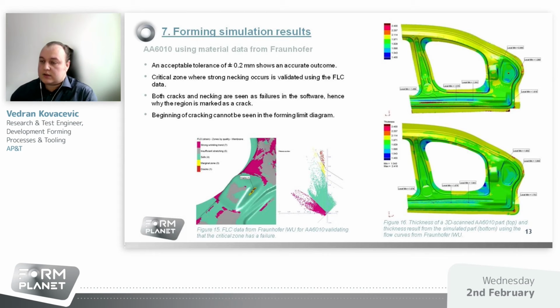Looking at the 6010 result, the simulation also shows accurate thickness behavior. The deviation in the critical zones is within plus minus 0.2 millimeter, and the zone where the strong necking occurs is validated with the FLC data from Fraunhofer.